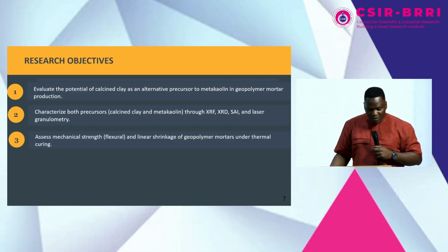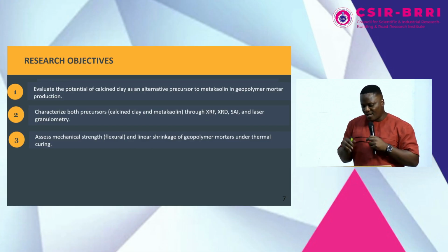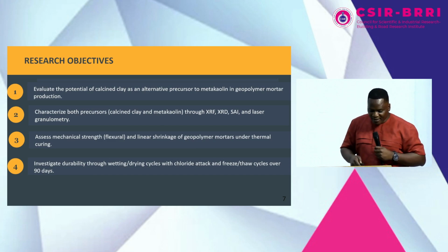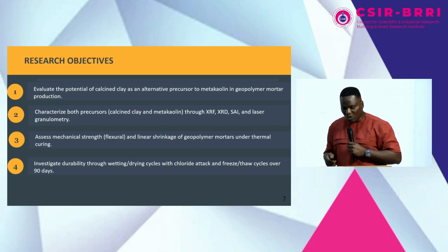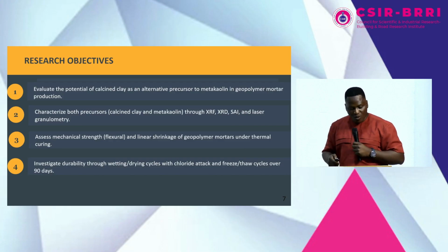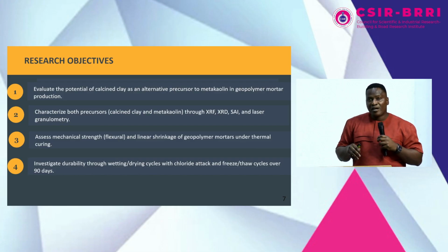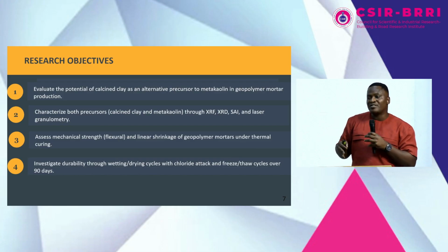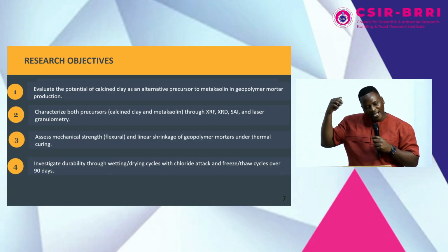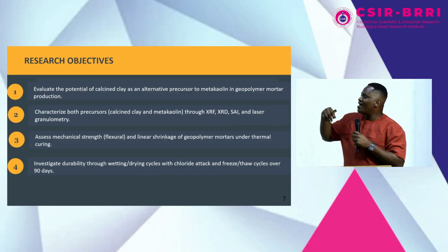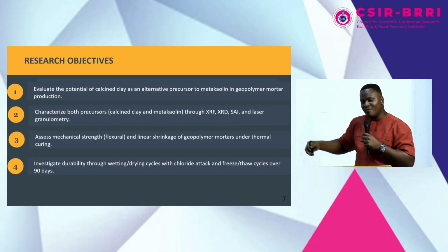Also to assess mechanical strength and linear shrinkage of geopolymer mortar under thermal curing. So we are going into a bit of durability to see how the material fares in terms of shrinkage, whether it expands or it shrinks when you subject it to some environment. And also to look at the durability through wet drying cycles, chloride attack and freeze and thaw cycles over a period of 90 days. Now, the wet drying cycle is that after preparing your material, one of the indicators of durability is that you have to subject it to an alkaline environment, an acidic environment, or a saline environment, just like around the coastal areas. So what you do is you subject it to the environment for a period, you take it out for a period of about 90 days to see how the material reacts.